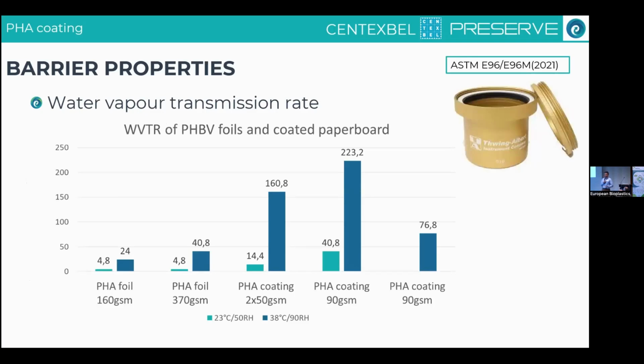Then for the other barrier properties, what is also important is the water vapor transmission rate. Here we compared some PHA foils and also PHA coatings under different conditions. For some of the latest developments, we get a water vapor transmission rate of about 70 grams per square meter per day. Since about 2 days ago, we got some better results, and we got this down to about 30 grams per square meter per day at 38 degrees. This is not quite yet what is expected from the industrial partners within the Preserve project, but we are about a factor 4 or 5 away at the moment. So we hope to achieve this within the next 2 years that the project is still running.